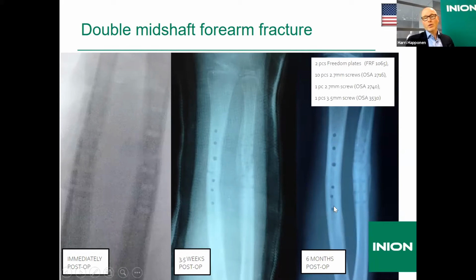The screw holes will stay in the bone until the implant has completely resorbed, which happens in around 2 years, and thereafter the screw holes can be filled with the bone. And we have evidence also for that, showing that within 3 to 5 years after operation, the small screw holes will be filled with the bone.